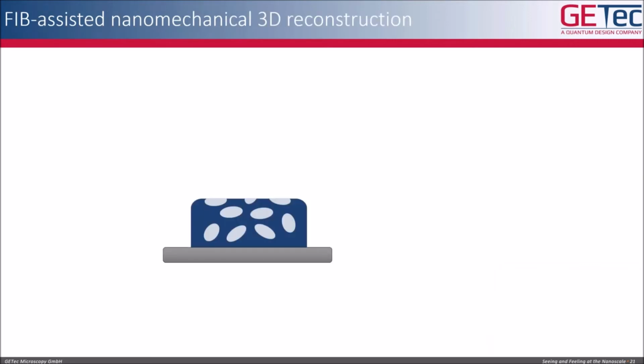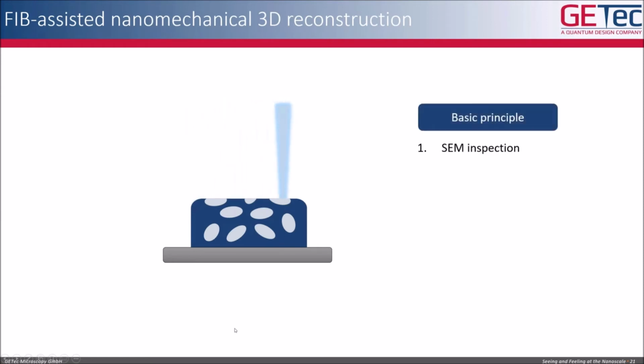And the basic experiment we did was using a polymer sample that you see here in blue, and this polymer had some harder beads encapsulated in the soft polymer. And what we did is we started first with an SEM inspection of the sample.